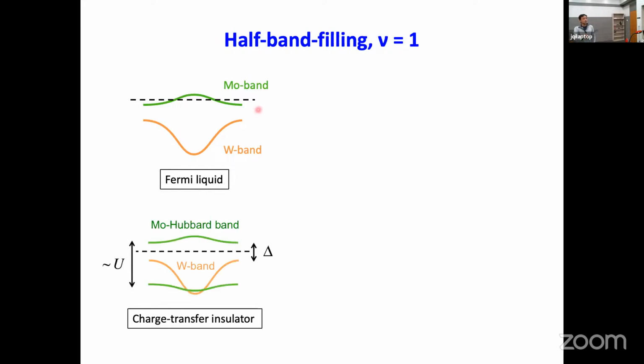And of course, if you turn on a strong correlation, the Moiré band, you expect it to split into the lower and the upper Hubbard bands. As a result, the Fermi energy is now located inside the gap of this lower and upper Hubbard band, and the lower and upper Hubbard bands are separated by an energy scale on the order of the on-site U.